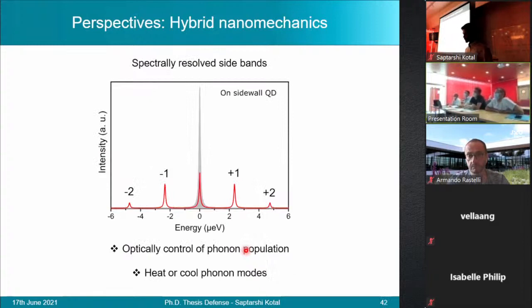Finally, we can use nanocavities for hybrid nanomechanics as well. Now, if we look at the spectrum of a quantum dot placed on the sidewall of the nanocavity, we see that even the first flexural mode generates a broadening which is in the spectrally resolved regime.